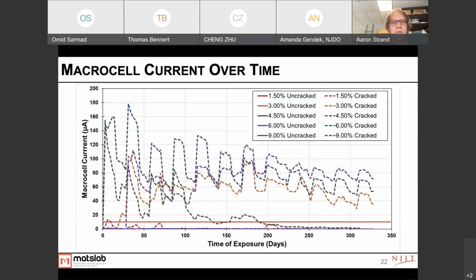So moving into the macrocell current over time for all the specimens, the dashed lines represent all of our cracked specimens, and the solid lines represent all of our uncracked specimens. And we can see that all the cracked specimens above 3% showed a macrocell current that was above the threshold value. Though it's interesting to note that over time, the 4.5 did start to drop back below the threshold. And this could be due to binding or closing up within the system, not allowing any of the chlorides to penetrate further.